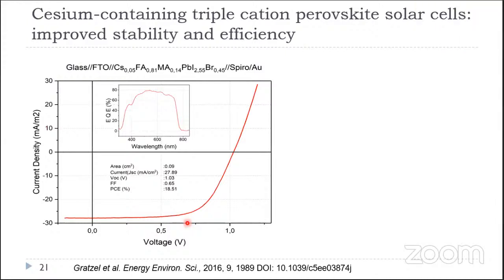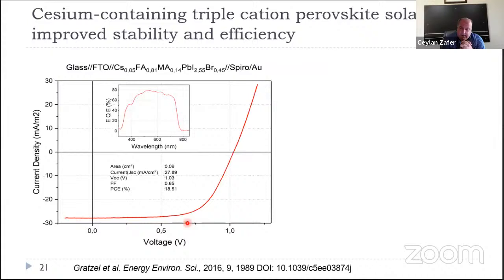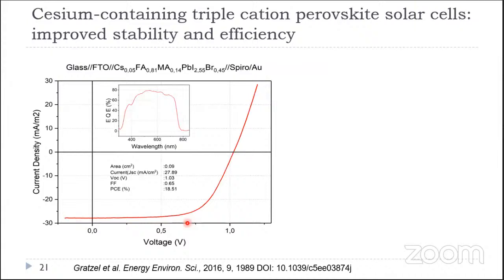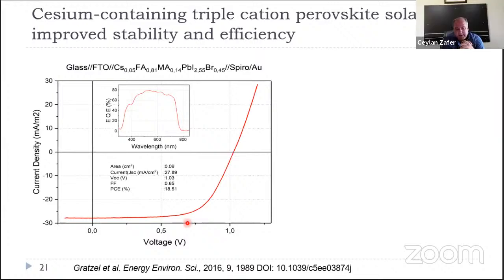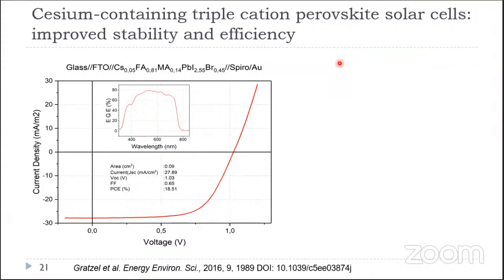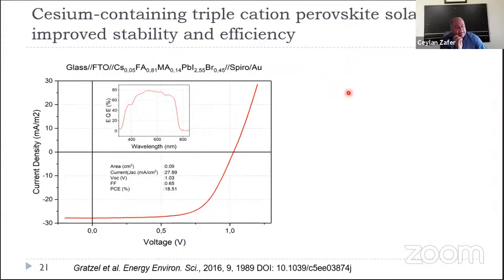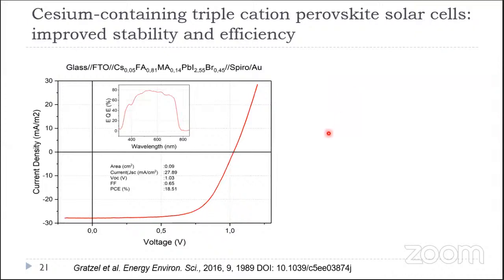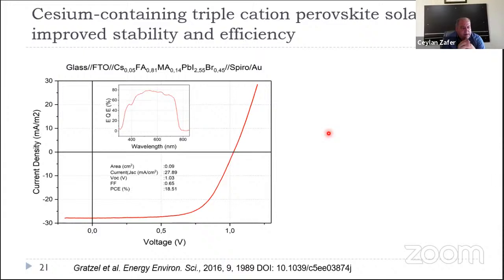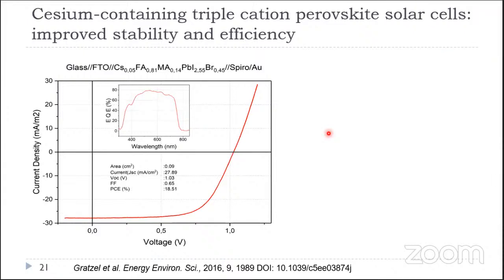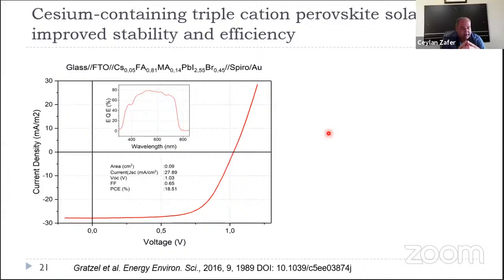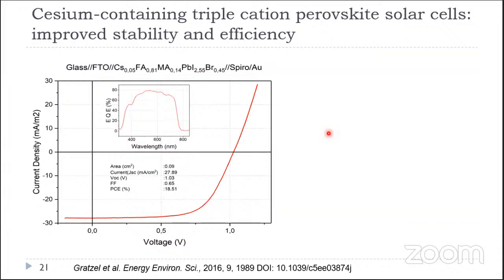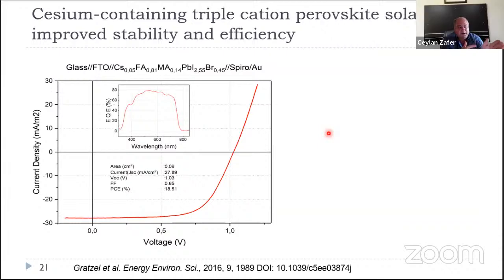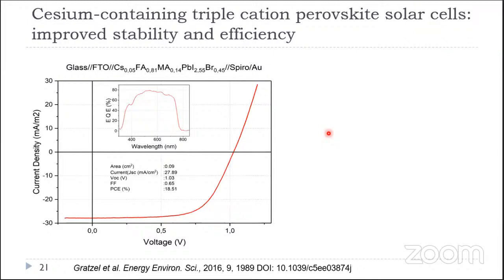And then nearly 5 years after the publication of the first paper on perovskite solar cells from the Grätzel group, came a very important paper giving us information about the triple cation perovskite, because the perovskite is a very interesting material. With only one cation, it doesn't make a very stable crystal, and the crystal should be stabilized with additional cations. And there are different phases which are non-photoactive for perovskite solar cells.